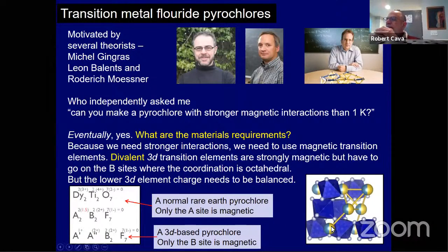Yeah. So the pyrochlore is two interpenetrating lattices of tetrahedra, but the tetrahedra in one case for the lanthanides are made of 7 coordinates with oxygen, and the other ones are 6 coordinate with oxygen. And the 6 coordinate with oxygen can then be a transition metal. And once you can put a transition metal there and a non-magnetic atom on the other side, you can get the interactions to be dominated by transition metal magnetism, which is hundreds of degrees, can be 100 degrees instead of 1 degree, because they're 3D based, not 4F based.